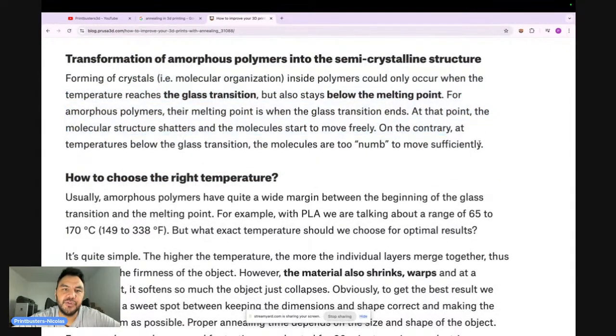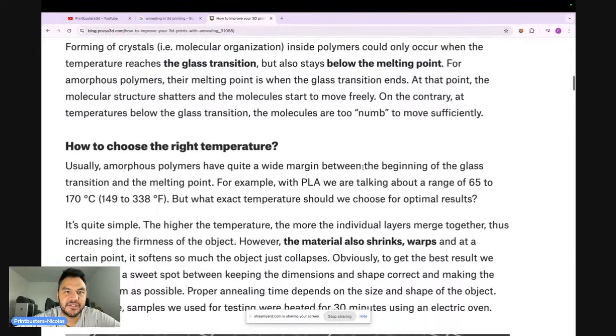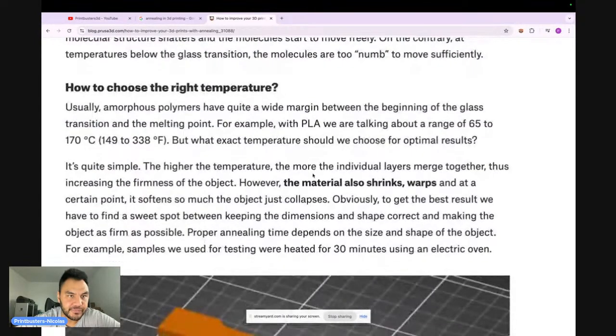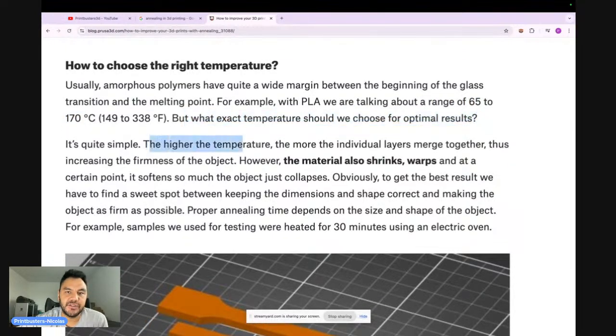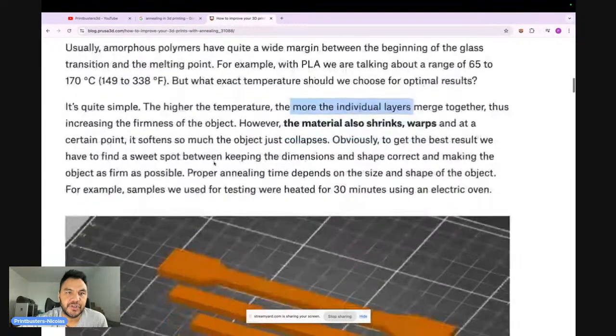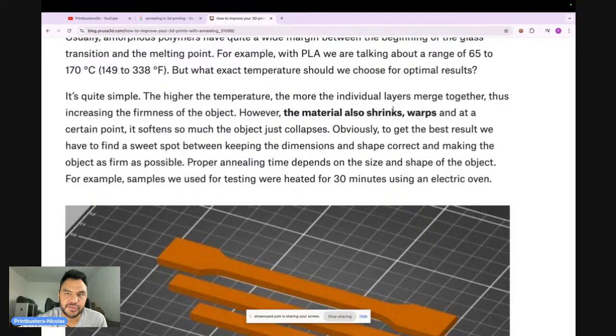In which way would you have understood the best the difference between the glass transition temperature and melting point? How to choose the right temperature? Usually amorphous polymer have quite a wide margin between the beginning of the glass transition temperature and melting point. For example, PLA, we are talking about a range of 65 to 170. It's quite simple. The higher the temperature, the more the individual layers merge together, thus increasing the firmness of the object. However, the material also shrinks, warps, and at a certain point it softens so much the object just collapses. Obviously, to get the best result, we have to find a sweet spot between keeping the dimensions and shape correct and making the object as firm as possible.